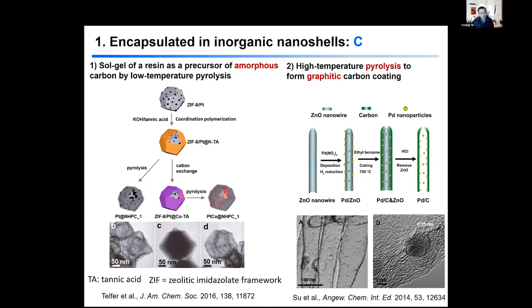Okay, if you do cation exchange, you can do that partially, and you can introduce cobalt into the system. And then if you do pyrolysis, you end up with another shell with the bimetallic nanoparticles inside. So if you do low temperature pyrolysis, you get amorphous carbon, but if you control the reaction at really high temperature, for example, 700 degrees C in this case, we can convert the coating into crystallized carbon, basically graphite. And then if you remove, for example, the template zinc oxide, you end up with metal nanoparticles of palladium decorated inside a carbon nanotube.